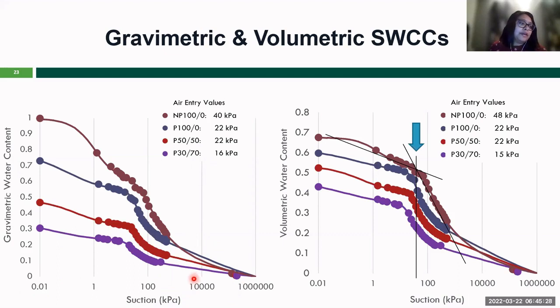And we saw that for non-polymer material, so the non-treated material, has a higher air entry if you compare with both plots. So you see the similar pattern, and also for other materials, it's almost the same, identical values that we have seen for the 2 different presentations that we have here. And then we have seen the different shapes for the polymer treated materials and the non-polymer treated materials. So that's probably one of the significant behaviors we can see because of the residual hydrocarbon. We see the different types of behavior for polymer treated and non-polymer treated.